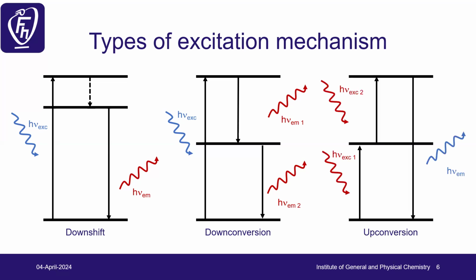photons can be emitted. And at last, we have the up-conversion system, which is now quite popular in inorganic materials. You can excite with low-energy photons such as 980 nm. You have ytterbium as a sensitizer, and then you use erbium or neodymium to emit at higher energy, so you can emit in the green or red part.